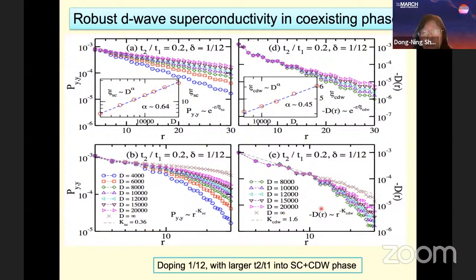Here we also show the CDW, the pair density correlation. Consistent with having a CDW phase, the density correlation also decays in a power law way, but with a larger exponent compared to the superconducting correlation. So superconducting correlation is also very strong in this coexisting phase.